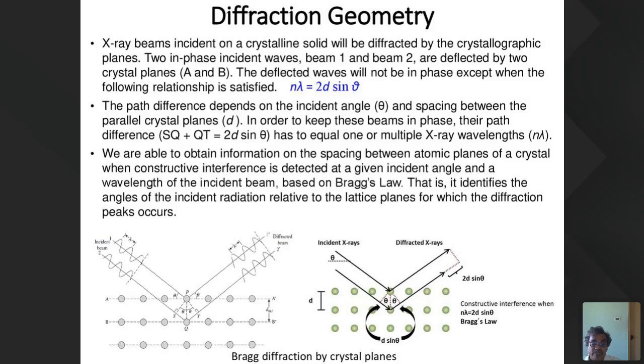That means constructive interference. We are able to obtain information on the spacing between atomic planes of a crystal when constructive interference is detected at a given incident angle and wavelength of the incident beam, based on Bragg's law. When it satisfies Bragg's law, it identifies the angle at which the diffraction peak occurs. That means a diffraction peak can be seen.